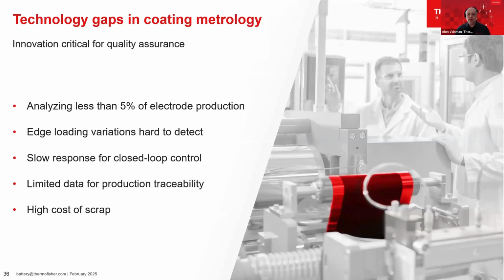As battery technology continues to develop, so does the need for more advanced metrology tools. Conventional single-point sensors only interact with a small fraction of the surface of the electrode, usually less than 5%. Variations in loading on the edges of the coating are difficult to measure, and the time it takes to collect data for representing a loading profile is measured in multiple seconds, slowing down the ability to respond to process changes.